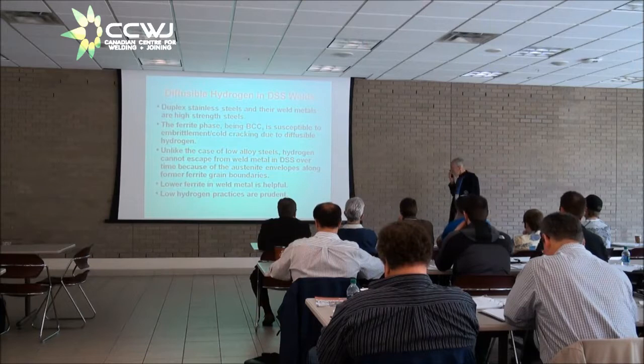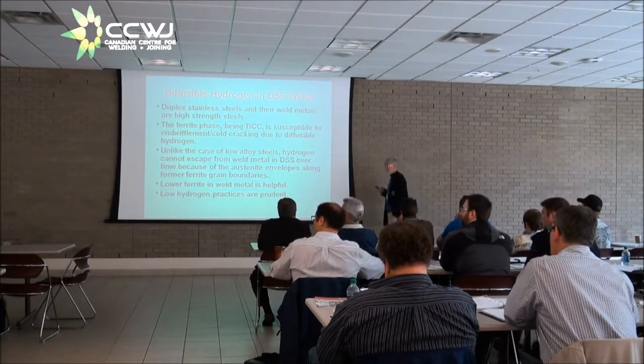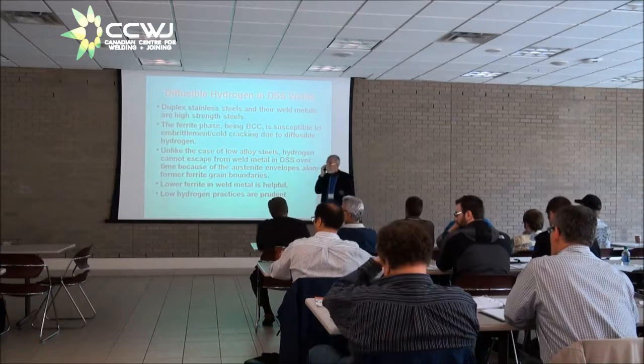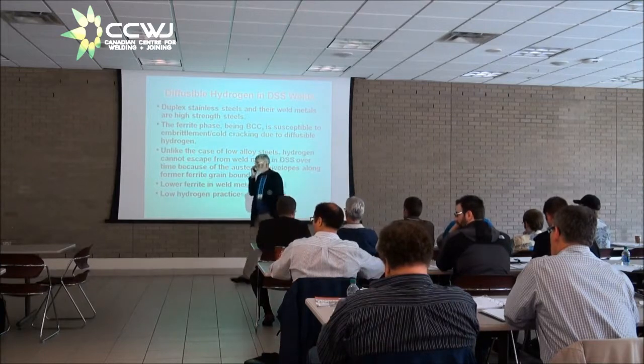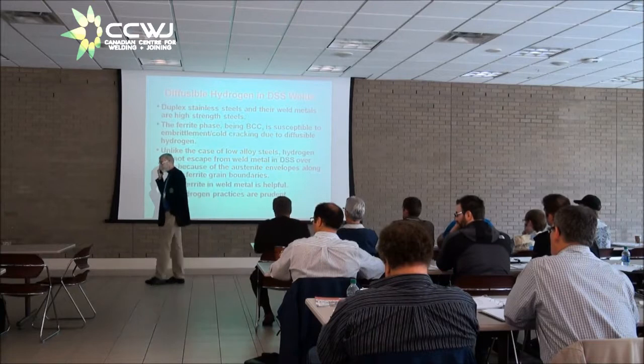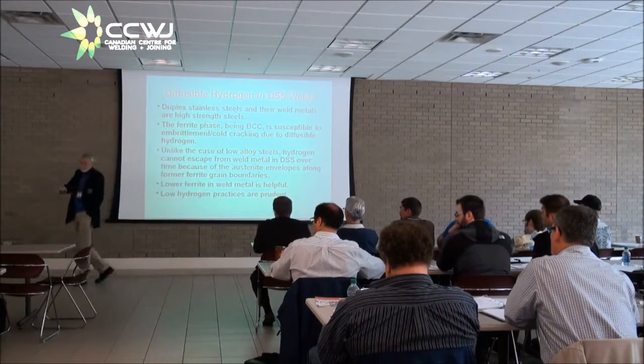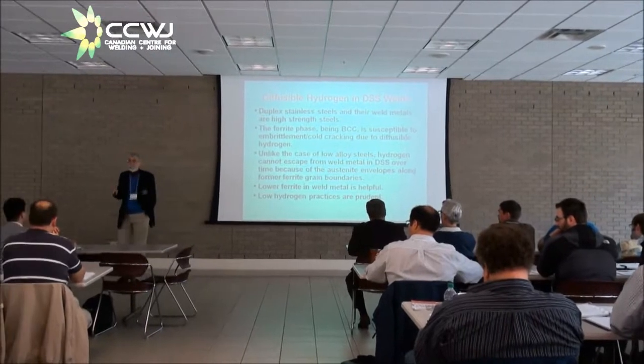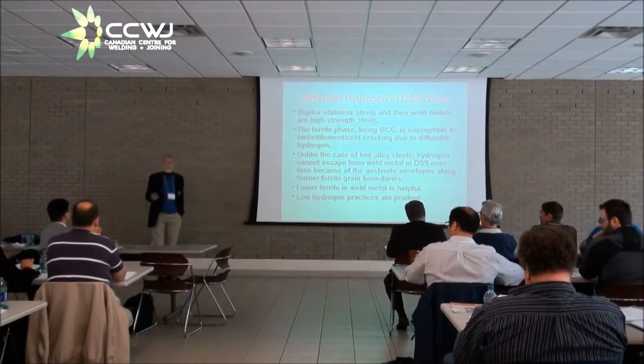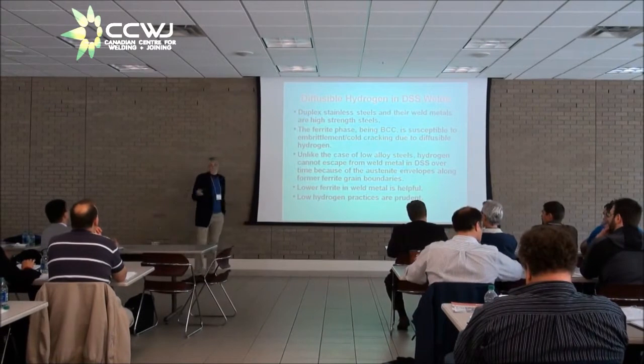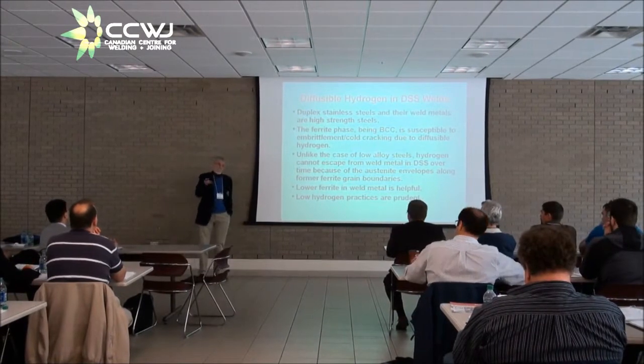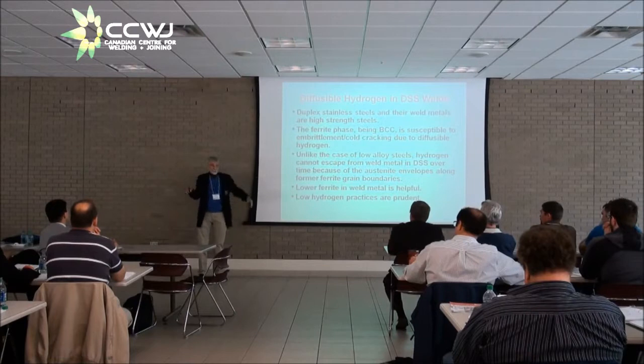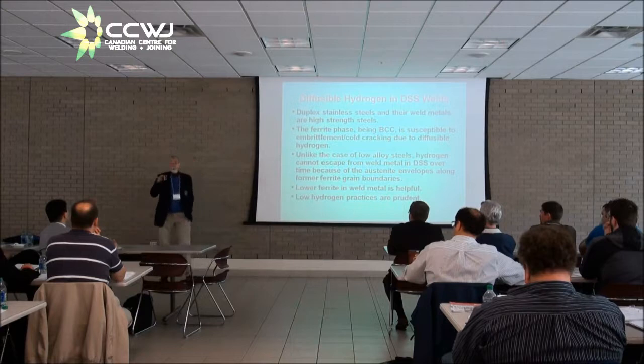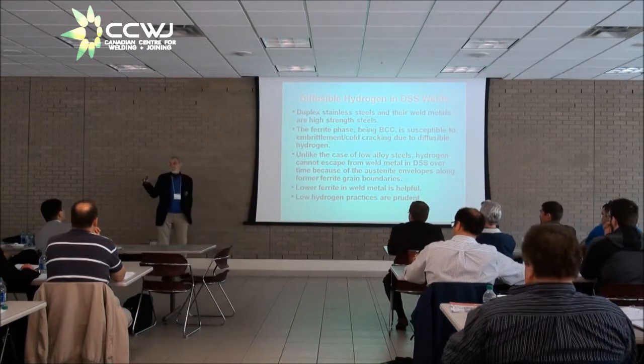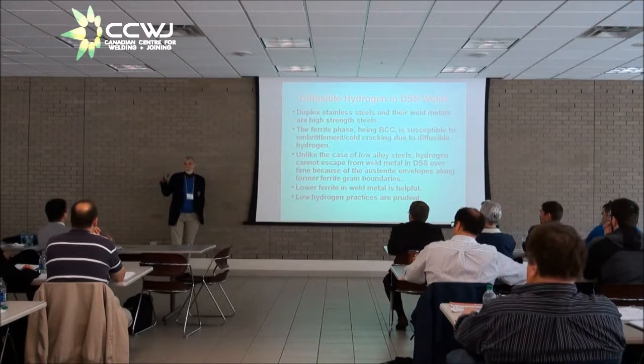There was a 2205 pipeline, Fred, you probably remember this one, in Malaysia, back in the early 80s, I think it was. 2205, welded with covered electrodes. And it was welded above ground on stands because the area where it was being laid was swampy. So they didn't put it into the trench until after all the welds were made. And when they went to lift the pipe off the stands with a whole series of cranes and lay it into the ditch, they very slightly deformed it because not all the cranes lifted at the same rate, and welds broke.